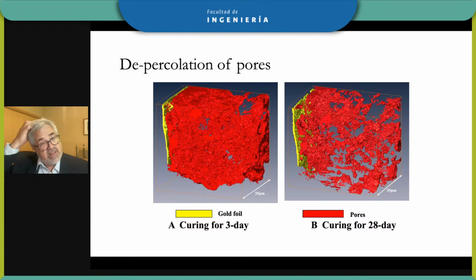And so these are examples where we had samples made with a foil here on one side. I put this in gold in yellow color. We wanted to do this because of our interest in what's called the interfacial transition zone. So we wanted cement to be against an impermeable surface. And then over here, this is for 3 days. Now it's for 28 days. And what we could do is analyze the porosity as a function of distance away from the gold foil, and gives you a sense of the size and therefore the impact of the interfacial transition zone.